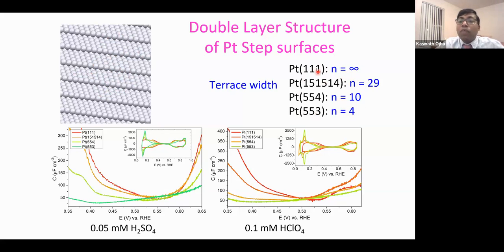So basically 111 does not have steps at all, so that's like an infinite number of terrace atoms. And then 15, 15, 14, so the number of terrace atoms is 29. So basically we have a 29 atom width of the terrace. And then 10 and 4. So basically we increase the number of steps in the surface.